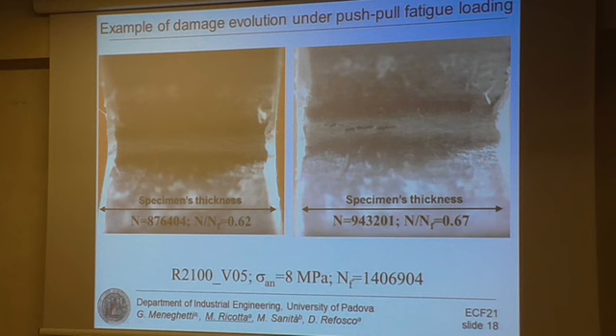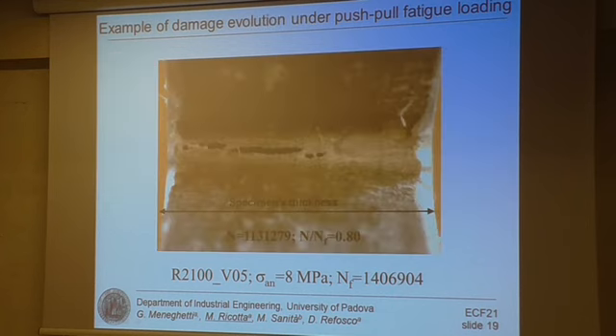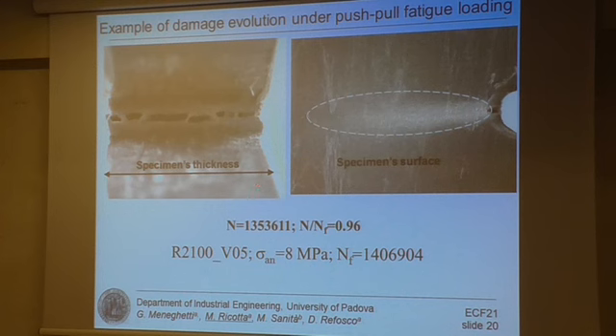Here this picture is taken at 62% of fatigue life, and we can see here at 67% of total fatigue life, formation of some elongated voids in the thickness direction that propagate at 80% of total fatigue life. And here we can see that we found practically a single big void completely developed in the thickness direction at 96% of the total fatigue life. But if we observe the specimen from the surface, we can see only a material whitening without any cracks appearing in the specimen surface.